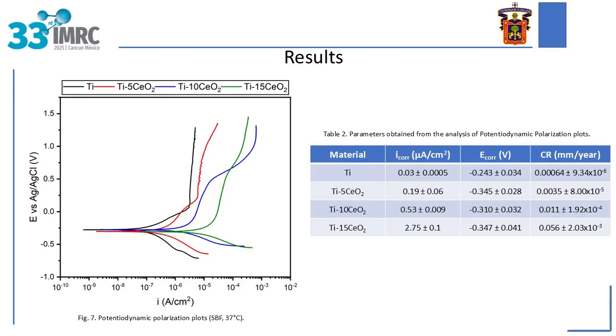A preliminary analysis of the potentiodynamic polarization curves indicates that the addition of ceria to titanium reduces the corrosion resistance of the composite compared to the pure titanium sample. These observations are corroborated by the parameters calculated and summarized in Table 2. As the percentage of reinforcement in the material increases, the current density increases by an order of magnitude, which decreases the corrosion resistance. However, the decrease is not critical, and its values are in an acceptable range for biomedical applications.